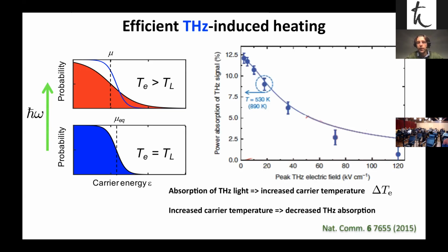And in the case of graphene and incident terahertz light, I'll show you some earlier results we obtained a few years ago, where if you use relatively low intensity of your terahertz light, you get an absorption of, say, 10–12%. That's just your free charges being accelerated by the terahertz pulse. That's your typical Drude absorption. Then if you keep increasing your electric field strength, you absorb less and less. So this is a saturable absorption effect, which is a nonlinearity caused by the fact that in this hot state, your conductivity is lower. And if your conductivity is lower, you absorb less terahertz light.